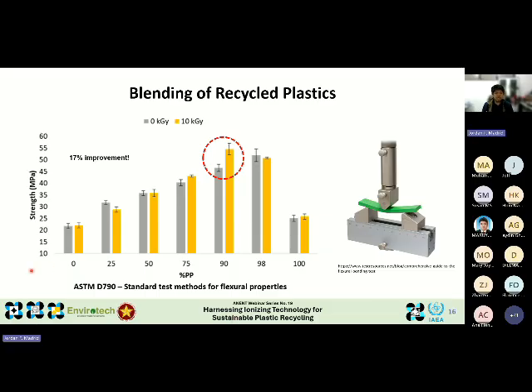So the results that we've obtained turned out to be very interesting. We observed a clear trend of increasing flexural strength with increasing polypropylene content, particularly around 80 to 90% polypropylene. On top of that, when we irradiated the blends at, say, 10 kilogray dose, the flexural strength increased even further. From these findings, we were able to make an initial estimate of the optimal formulation of our products, and this is a very important step moving forward to the subsequent phases of the project implementation.